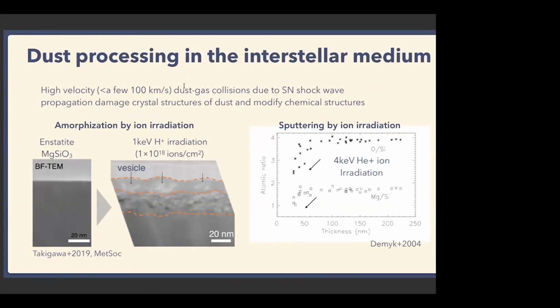So the dust is exposed to accelerated gas molecules like hydrogen protons or alpha particles. These hydrogen or helium ions are accelerated by the supernova shockwave propagation. The accelerated gas hits the dust surface and damages the crystalline structures. This is an experimental study of how the crystalline structure changed due to hydrogen irradiation. The beautiful surface is gradually damaged, this region is completely amorphized, and some vesicles appear on the very surface.